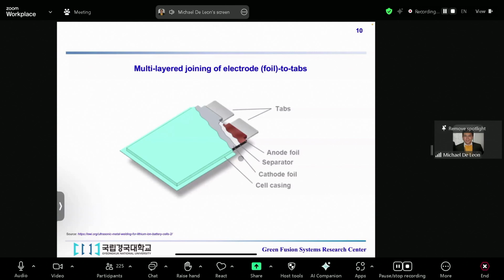Here we work with high purity materials to mirror the real battery components, with thickness ranging from 100 microns to 200 microns thick. We use copper with 99.9% purity, such as C1220, and aluminum with 99.6% purity, such as A1050 aluminum. Precision cuts were made into shape 50 millimeter by 20 millimeter test coupons.